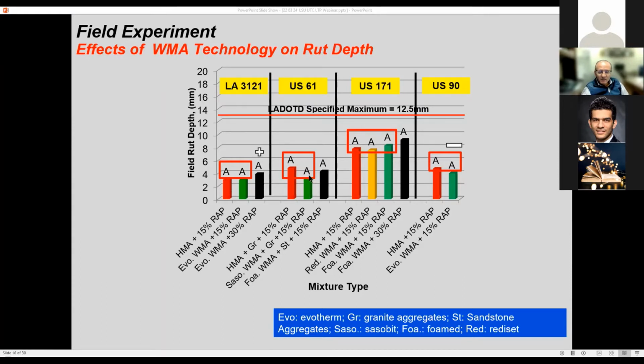And those A's, basically, these are the statistical grouping. So they are either statistically similar or statistically better or statistically worse. If you look at, for example, this project 3121, we increased RAP content. Intuitively, you would think that rut depth should decrease. However, this shows that even though it did not decrease, it had a slight increase.